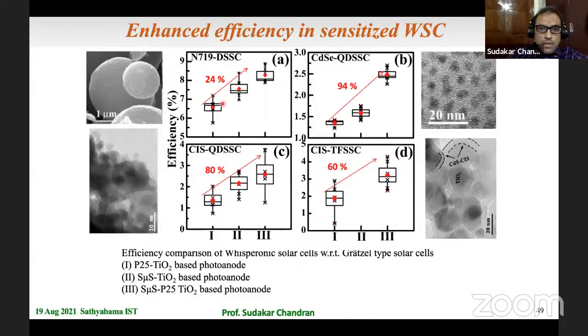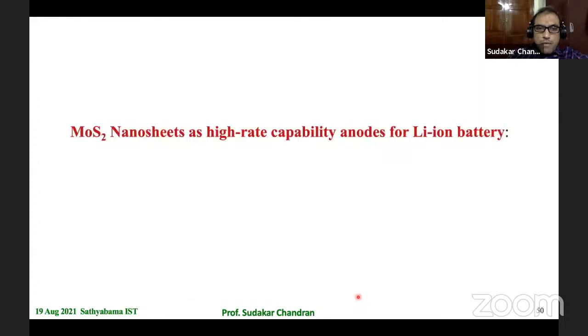This is a typical dye sensitized solar cell, the Gratzel type. And then we have tested copper indium disulfide quantum dots. We also made thin films of copper indium disulfide on these spheres. So all of them show a large extent of increase in the efficiency. And we call this particular modified Gratzel type solar cell a whisperonic solar cell, because the whispering gallery mode helps in enhancing the efficiency a lot.